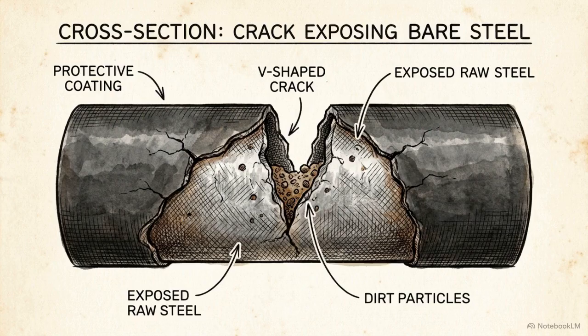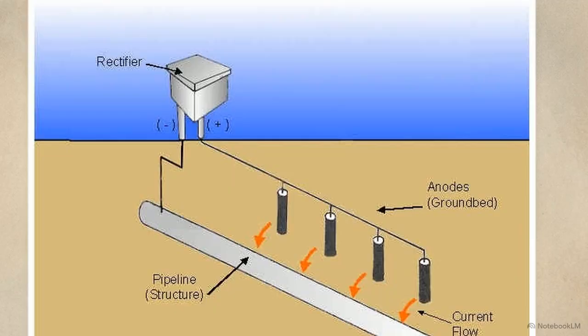But physical breakdowns or defects in this passive layer frequently occur from installation or soil stress. These defects are called coating holidays. The moment a coating holiday exposes the bare steel, corrosion is inevitable. To prevent a catastrophic failure, operators rely on a secondary, active defense system. This active defense is Impressed Current Cathodic Protection, or ICCP.